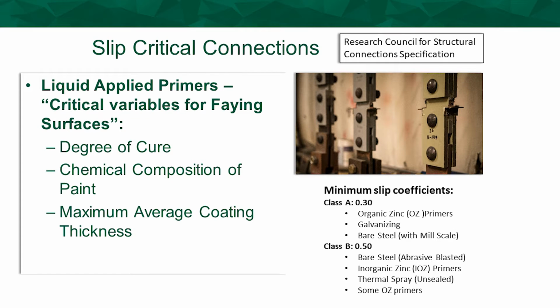So you want to make sure you know what you're using, based on the proper slip coefficient requirements. And again, here we go talking about slip critical connections. The Class A is 0.3, which allows organic zincs, galvanizing, and bare steel with mill scale. Class B allows bare steel to be abrasive blasted, inorganic zincs, thermal spray, which is typically your metallizing, and some organic zincs. And when you're dealing with liquid coatings, you want to make sure you understand the degree of cure.